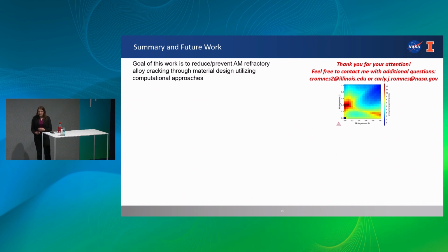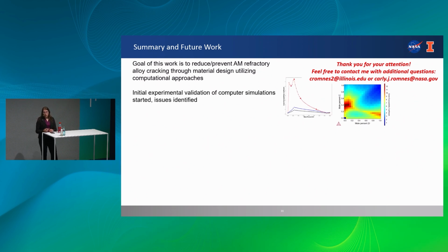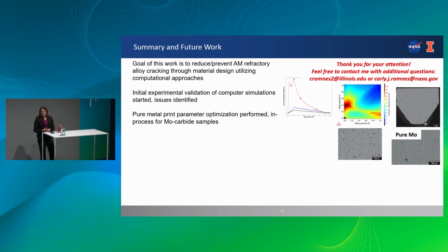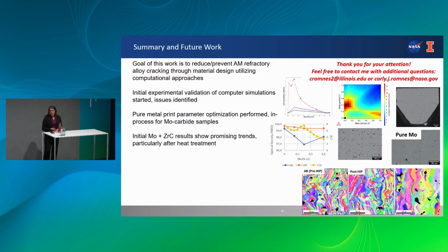Just to wrap this up, our goal of this work was to help reduce and prevent cracking and porosity in additively manufactured refractory materials. We wanted to utilize computational tools to help us design these materials and determine what was the best approach. We started some initial experimental validation of these simulations and identified some issues with the designs. We did a lot of pure metal print parameter optimization, and this needs to be done for the carbide materials as well. But these initial results actually show some promising trends where we don't have this large increase in grain size after hipping, which is promising. We have a major increase in the density without having large grain growth, so this is good for mechanical properties